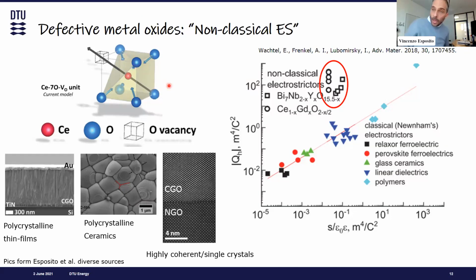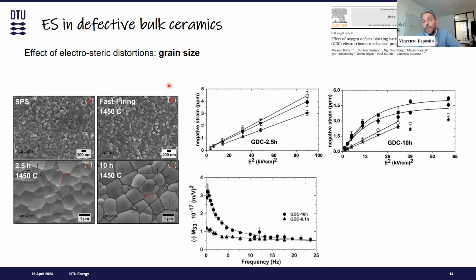So the first question that we have when it comes to a polycrystalline system, which is a bulk ceramic material, is what is the effect of the disorder, so the grain boundary or the grain size. And we've been analyzing the electromechanical properties for several years. And we saw, as you can see in these plots, that the grain size is actually affecting the electromechanical response, especially at low frequency. So if you see here in these plots that we have this linear relation between the square of electric field and the strain, which is typical of electrostrictors, there are also some not completely explained saturation effects. But what is actually important to notice here is that the electromechanical response changes as a function of the frequency.